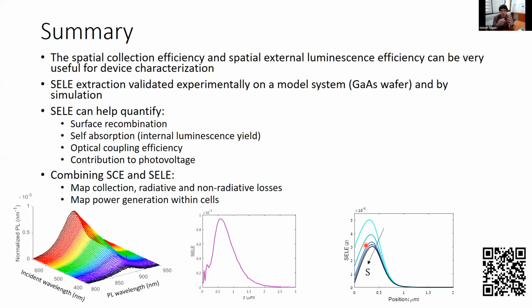The extraction of the SELE was demonstrated experimentally on a gallium arsenide wafer, and we believe that this kind of analysis can help quantify a range of material processes and device processes like recombination that is radiative, non-radiative, and contribution to the photovoltage. And we are now looking at applying this to a range of different material systems and devices.